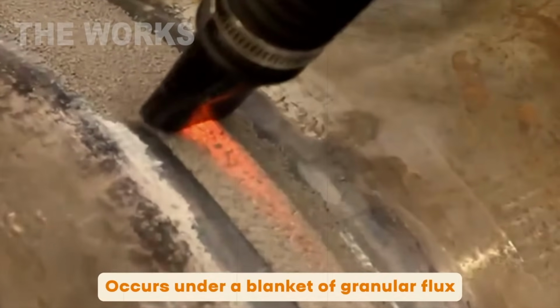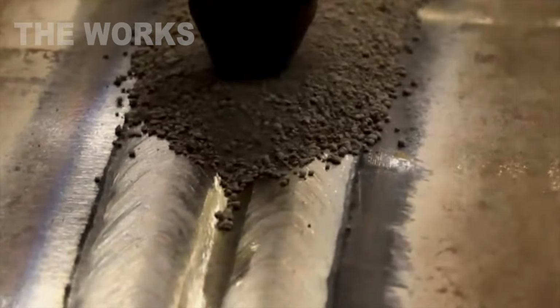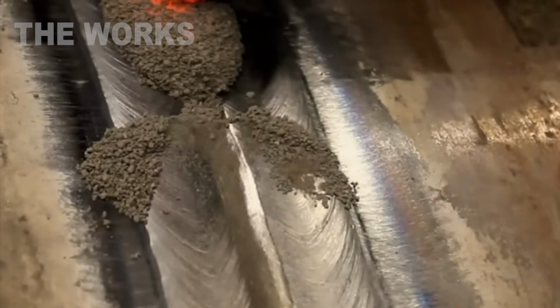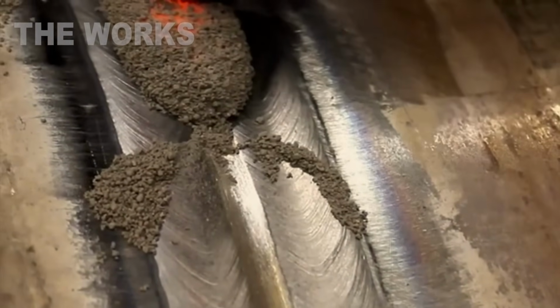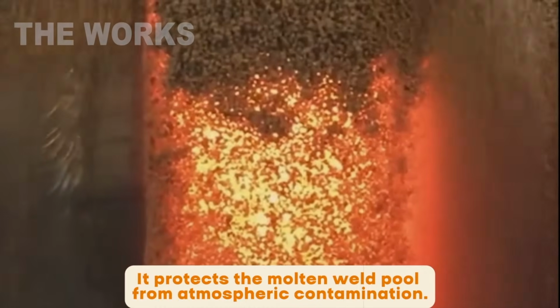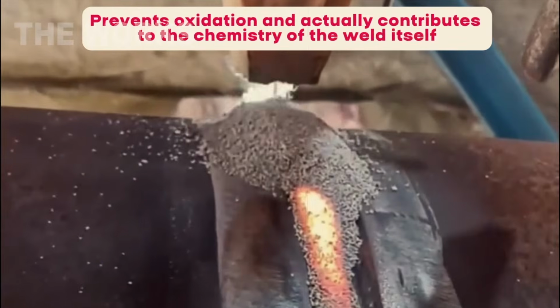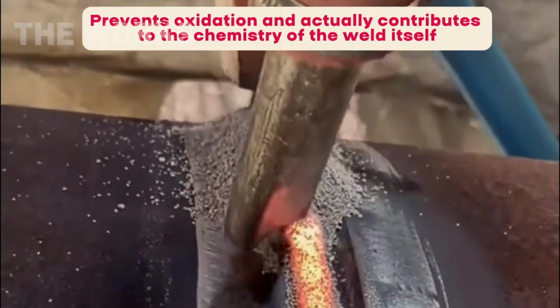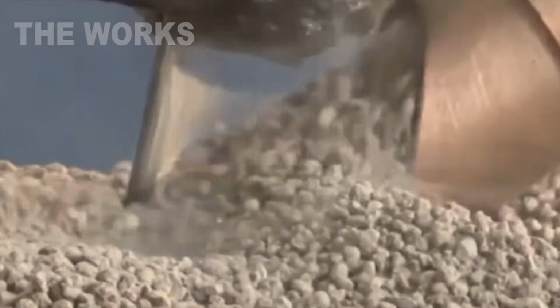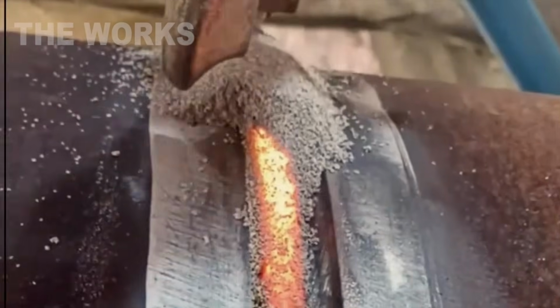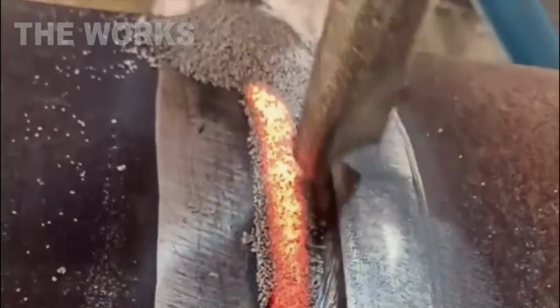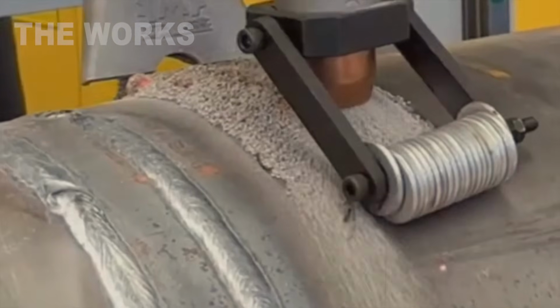This flux, which looks almost like coarse sand, performs several critical functions. It shields the molten weld pool from atmospheric contamination, prevents oxidation, and actually contributes to the chemistry of the weld itself. The setup is mesmerizing. A continuously fed wire electrode runs through the welding head, and when it strikes an arc to the base metal, it melts both the electrode wire and the parent material, creating a deeply penetrating weld.